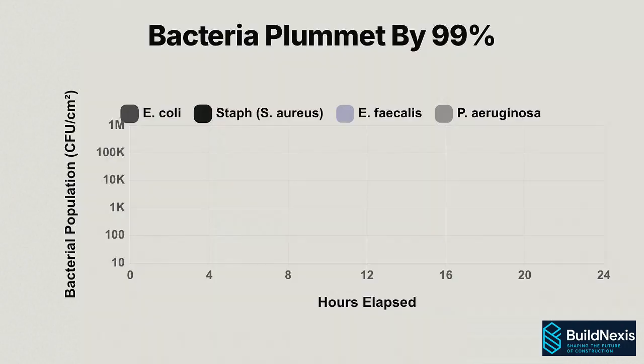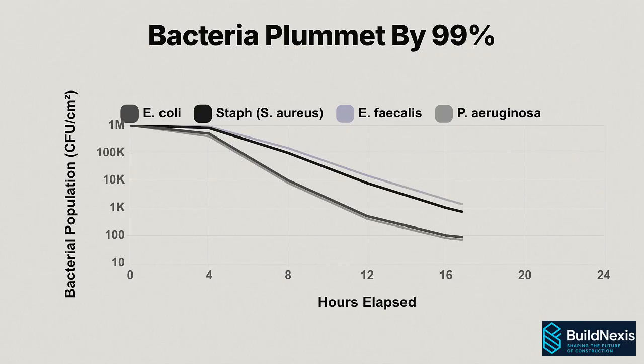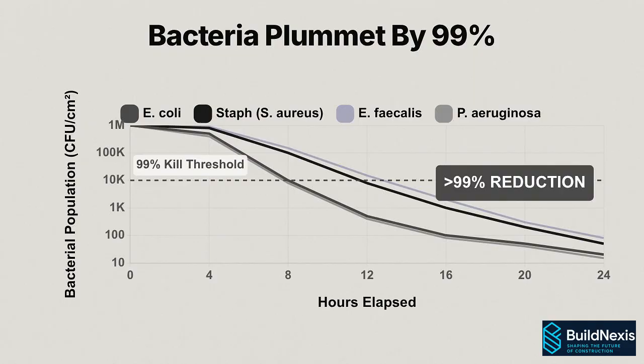On this test sample, tile 13S, the metallic silver clusters remained exactly where they needed to be, sitting securely on top of the glaze. This chart shows the biological results over a 24-hour period. When exposed to 4 major hospital pathogens, including E. coli and Staph, the bacteria populations plummeted, resulting in a 99% reduction.